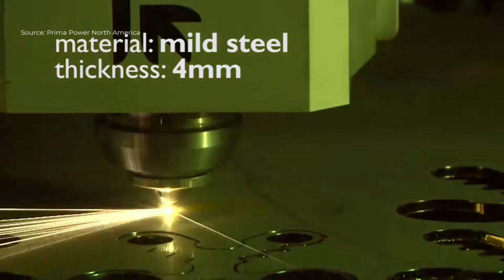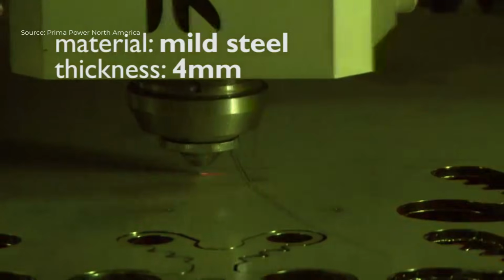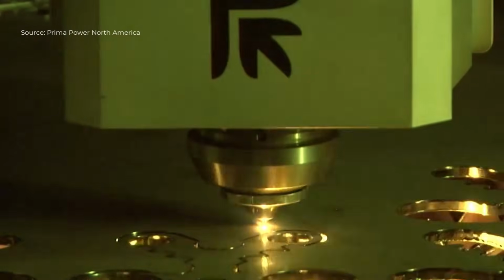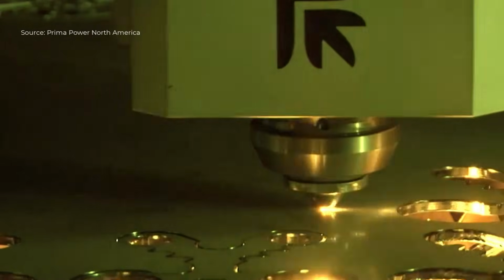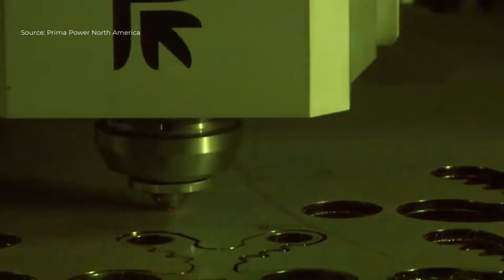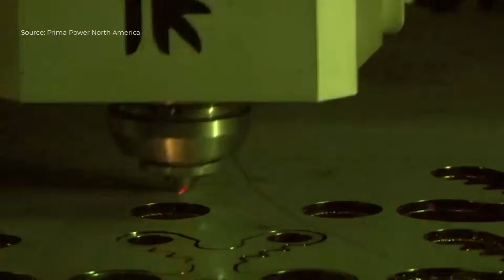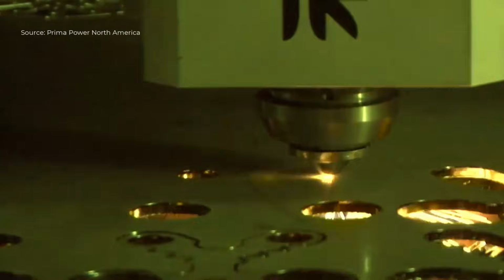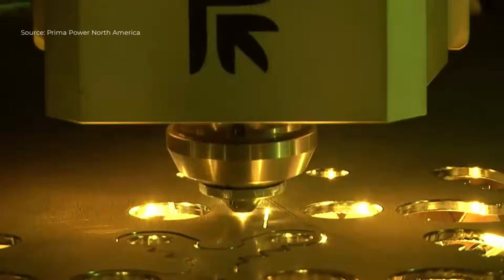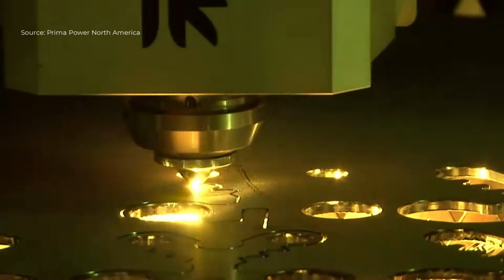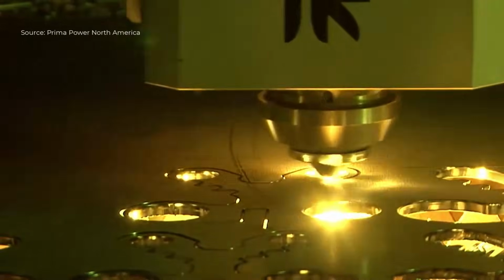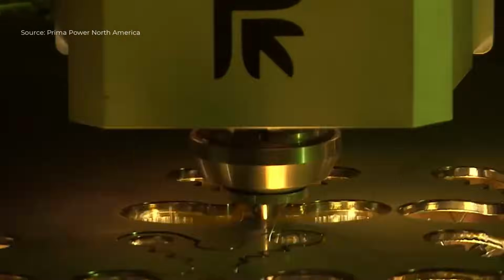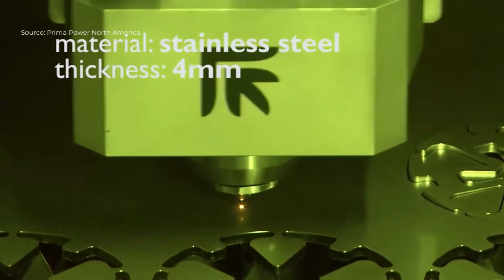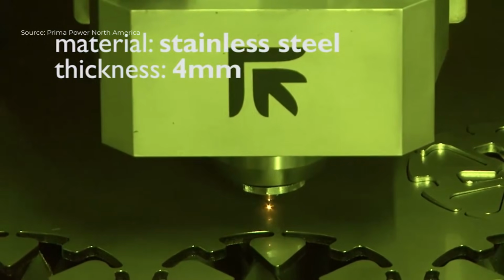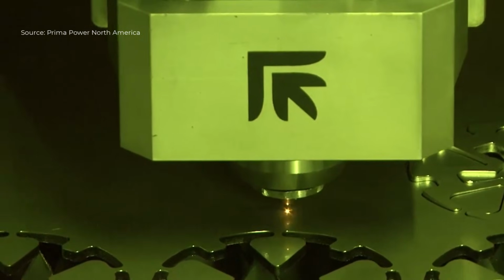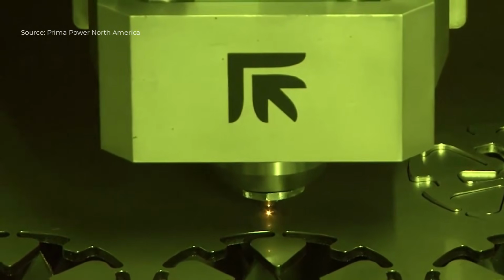After completing the mild steel cutting cycle, the machine transitions to stainless steel sheets with a thickness of 4 millimeters. The laser parameters are automatically adjusted to suit the different material properties. The cutting head lowers to the optimal focal distance, and the laser pierces the stainless steel with controlled energy delivery. During cutting, assist gas flows through the nozzle to remove molten material from the kerf, ensuring a clean cut and preventing oxidation. The machine maintains steady cutting speed, demonstrating its ability to handle medium-gauge materials with consistent quality and minimal heat-affected zones.